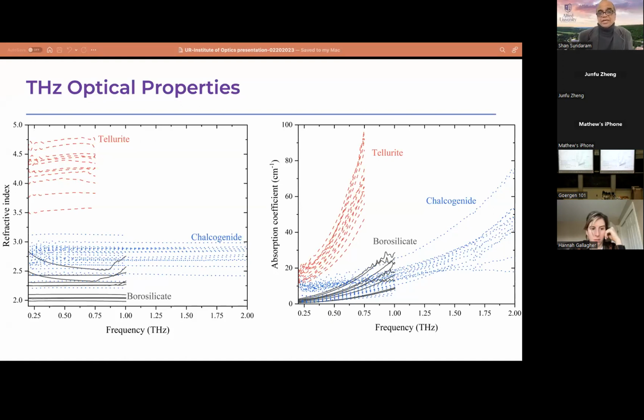So what I'm showing you is we also measured a whole family of tellurite glasses. These are tellurium-containing, rare earth-containing glasses made in our laboratory. And I've shown you the refractive index and absorption coefficient of all the glasses we have measured. You can see some of them hit the noise floor at various ranges. In chalcogenide, we could measure a little bit extended range, and for tellurite, the cutoff is even a little bit narrower here. But the important thing is you can clearly see three more or less distinct families with a distinct set of properties in the terahertz frequencies we are talking about. And I will show you a couple more correlations, and you will see some grouping happening here, okay?